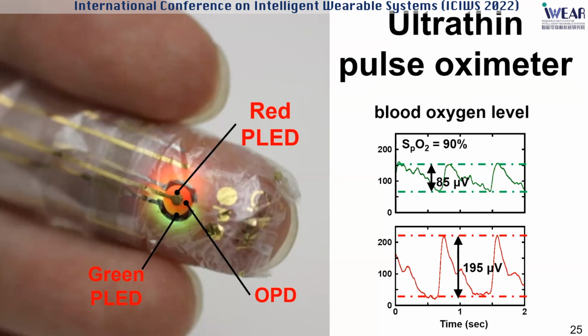Because it is kept to be super thin, the sensor attachment on fingertip doesn't cause any discomfort of wearing. Or even though user may move the finger slightly, the measured point doesn't deviate from the optimized position. So in that way, the ultra-thin device attachment realizes a fairly good robustness against the motion artifact. But this was just the single point detection.